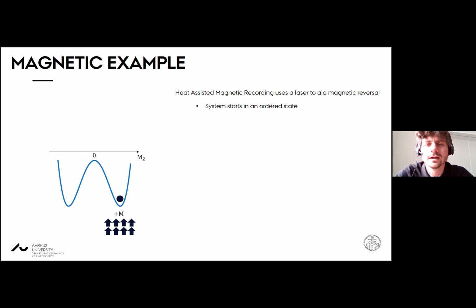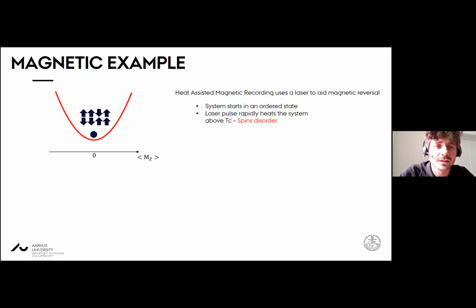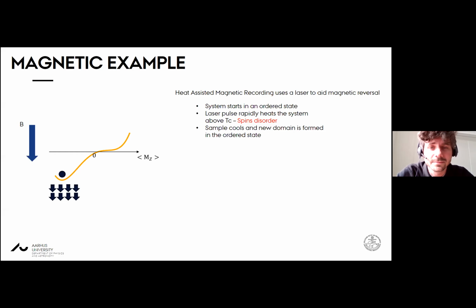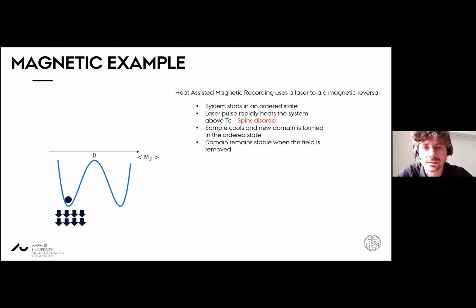So if we take the most recent magnetic recording technology, which is heat-assisted magnetic recording, the system starts off in the ordered state, but then it uses a laser to rapidly heat the system above TC. And when this occurs, the individual spins lose their preferential order and they randomize. Okay, and now we're in a state where MZ is equal to zero, but it's very different from the rotated state I described before. In order to induce the new state, you have to apply a magnetic field to the system, and this causes a preference to be orientated in the spin down configuration in this case, and allow the system to cool. And once the system has cooled down, you can take the magnetic field off and it will be trapped in the spin down state.